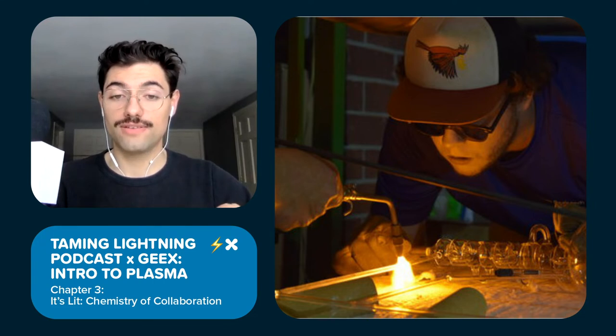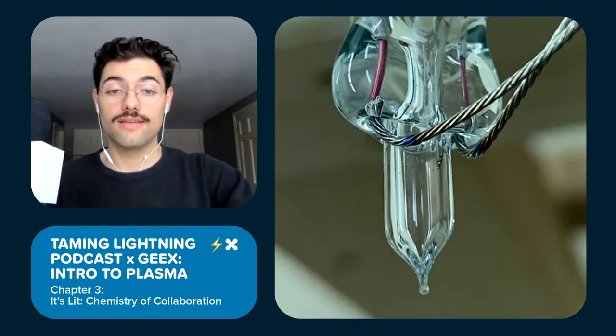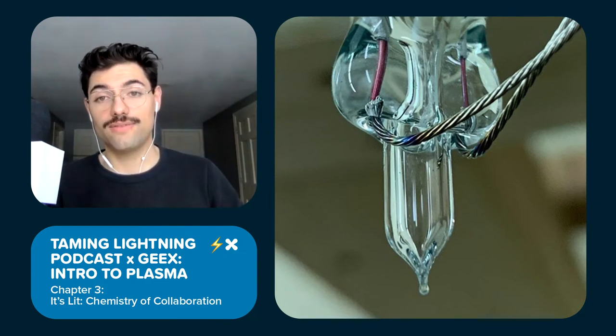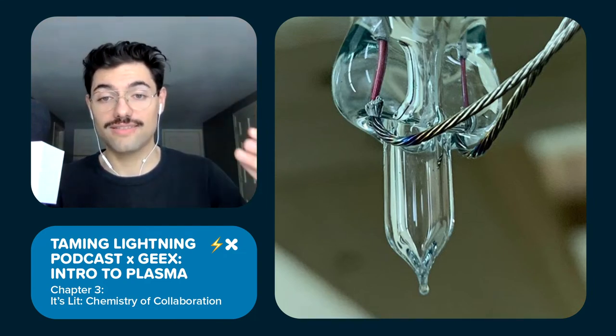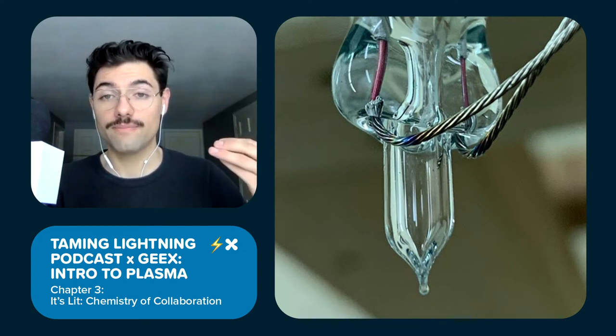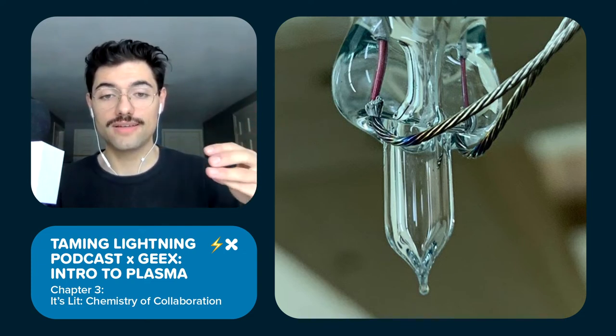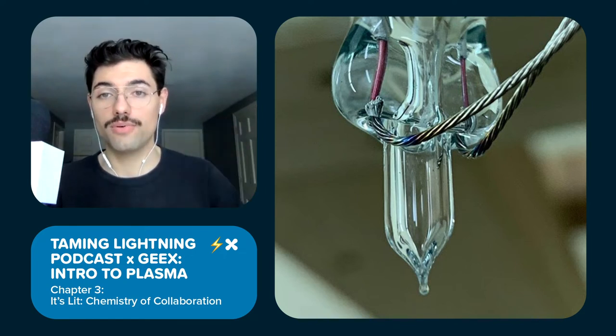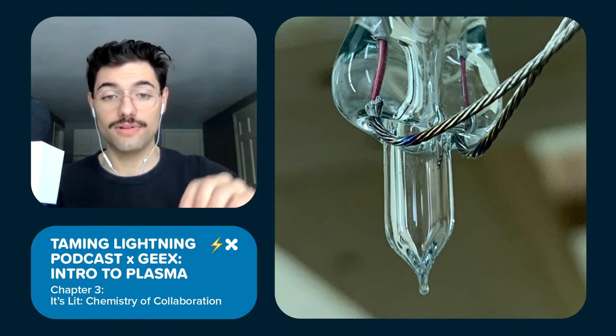And then also remember to try to keep your distance between the manifold and the electrode. So to execute the tip off, we're going to evenly heat in a concentrated spot on the tubulation, let the glass wall of the tubulation slowly collapse, and then pull away the vessel to create a gentle point on your piece at the end of the tubulation.